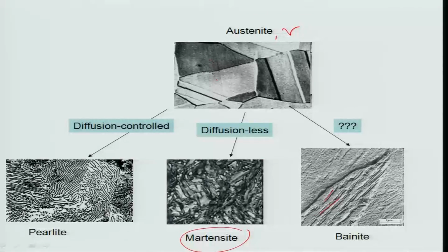As you understand from this slide, in steel I can take austenite and, just by varying the process parameters a little from left to right, create 3 different types of structures, and each of these structures will have different physical and mechanical properties. This is the beauty of metallurgy. You can take the same phase, cool it differently, and create 3 different microstructures. That is why steel is such an important and interesting subject. Okay, so I will now go back to the phase diagram.